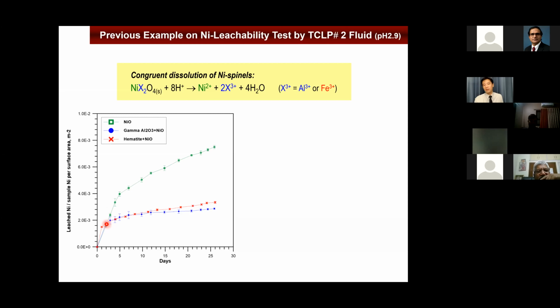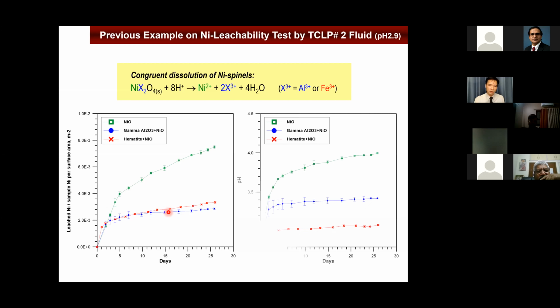In fact, you cannot tell the differences of the leachability of the nickel oxide compared to the new nickel spinel phases. But once you extend the leaching period to be longer, you start to see completely different behavior. The spinel phase can stabilize the nickel much, much stronger compared to the nickel oxide by itself.